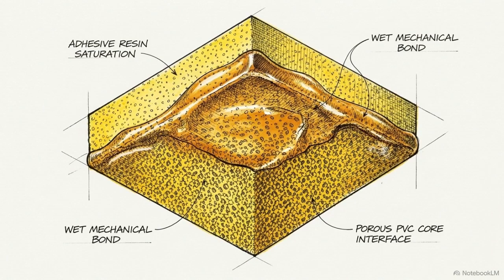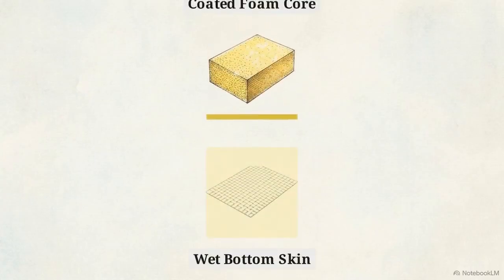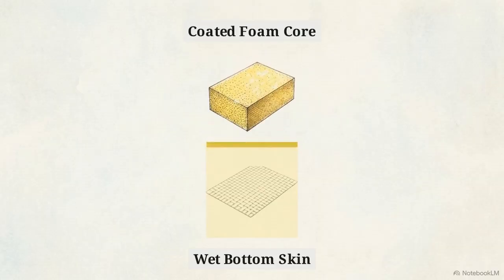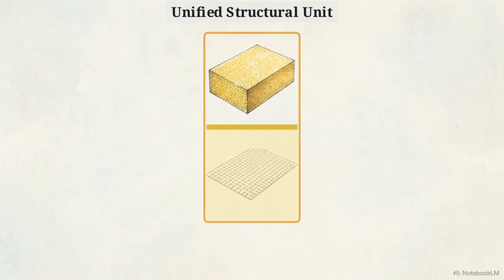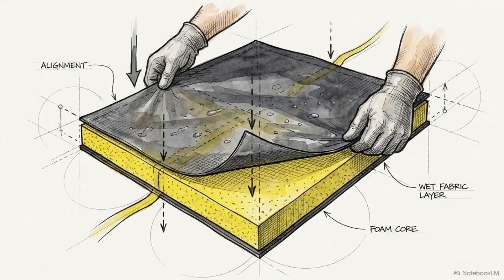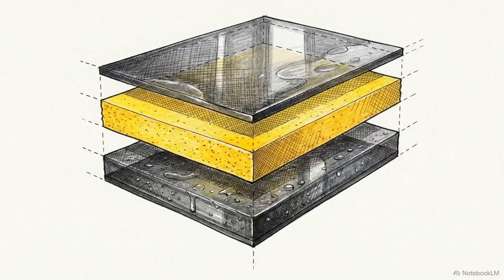Coating the bottom of the PVC foam core with adhesive resin fills the open cells on its surface, readying it for bonding. The coated foam is dropped directly onto the still wet bottom skin. This wet-on-wet contact allows the 2 layers to chemically fuse into a single unit. To close the structural envelope, a saturated top skin is aligned directly over the core. At this stage, the assembly is finished but vulnerable until it is compressed.